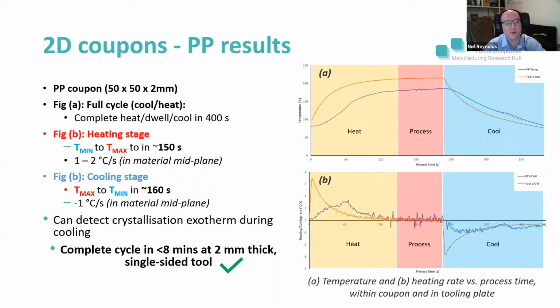So these are the results from the actual coupon testing. If you look at the graph on the right, you can see in orange the temperature versus time for the tool surface, and then in blue the mid plane of the 2 millimeter thick laminate. I've divided the graph into 3, so you can see the heat, processing, and cool stages. There's just under 60 seconds dwell in the middle, and we arrived at this cycle time based on visual inspection of the laminate, so basically trying to manufacture a fully consolidated laminate. The parameters that we've used translate into a total process time of about 400 seconds, so 6.5–7 minutes. So certainly under 8 minutes we can do a full heat cool cycle on a single-sided heating system.